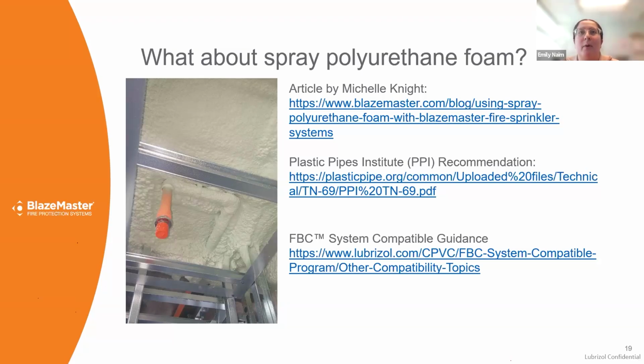So when the monomers lock together, they form a hard plastic, and all those additives that are incompatible with CPVC get trapped inside the foam bubbles, making it difficult to penetrate the CPVC surface. So essentially, the structure of the foam locks those additives, making it not harmful to CPVC. And the key to this proper foam is proper application. So the application should be even, not too thick. Make sure it's uniformly coated, covering everything completely, like the image on the left-hand side. If the foam doesn't foam up like we see in the picture, or is partially put on, this will leave the additives on the surface of the CPVC, and this will cause cracking and failure.